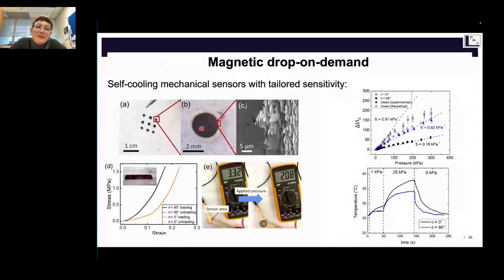And so it's a mechanical sensor. What we do is we apply pressure on it, and then you measure a variation in the resistance. And the design comes in handy because when you control the angles of the graphite in this sensor, and I'm coming to this plot here, you can tune the sensitivity of this sensor. If you have only vertical, it's not going to be very sensitive, but you can apply high pressure. If it's only horizontal, it's linear only at the beginning, and then you cannot apply very high pressure because then it's not linear. But if you have mixed orientations inside this pillar, you can extend the range where it's linear towards higher pressures.